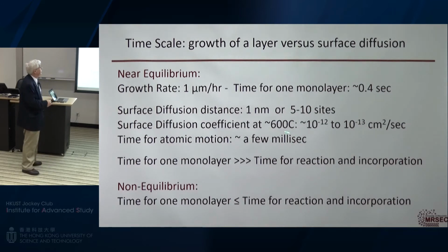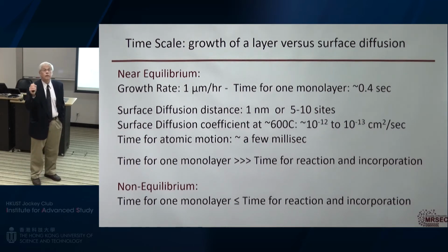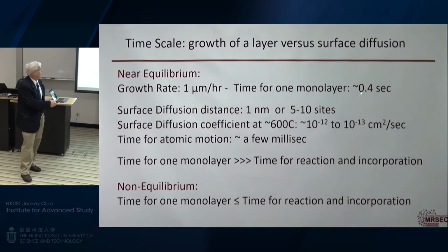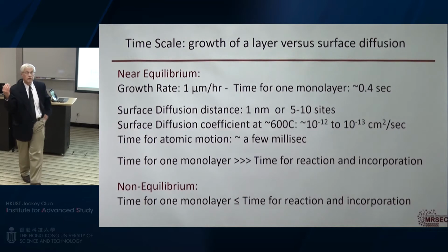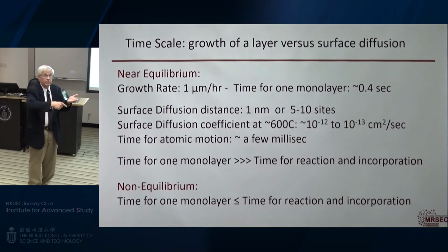And a typical temperature is 600. The surface diffusion coefficient is 10 to the minus 12 to 10 to the minus 13. So the time it spends looking for the right kind of spot to sit in is a few milliseconds. So an atom comes down, and within a few milliseconds, it'll find the right spot at these temperatures. On the other hand, another atom won't come by for another factor of about 1,000. So the time between atoms being added is very long compared to the time it takes for an atom to actually react and incorporate. So we have two big time scales. Atoms are coming down, and they have to find the right spot. That arrival rate is very small compared to how fast the atoms are moving. So all the atoms find the right spot, generally.